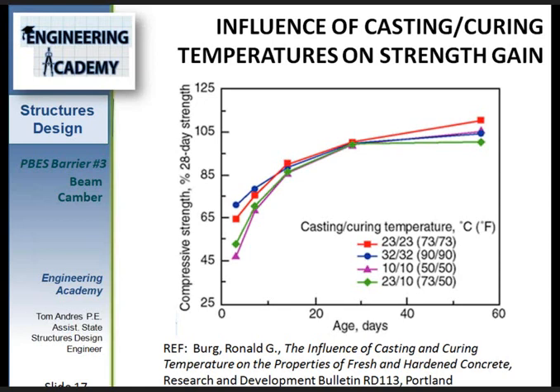Note that the first few days of curing typically correspond to the time that the strands are released, given typical precast bed turnaround times. The point here is that casting and curing temperature is one factor which influences the repeatability and predictability of camber.